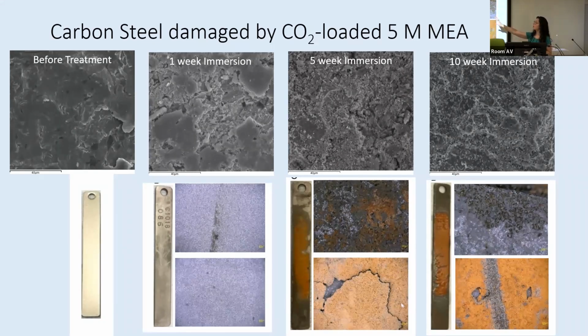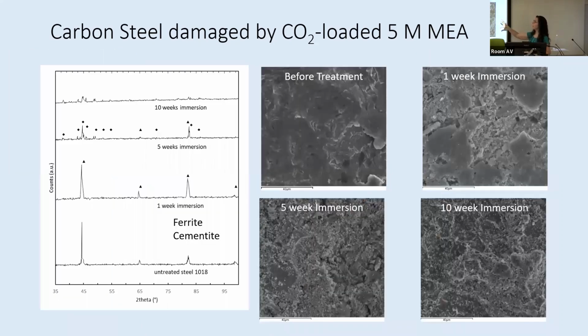One of the things we can see is that over the course of 10 weeks, we see increasing amounts of damage. Understanding that damage profile from a chemical and a materials point of view is extremely useful in establishing whether we've got approaches which can be used to keep this type of infrastructure material safe, which costs on the order of 25% of a stainless steel, maybe even less. So what happens during this process from a chemical point of view?